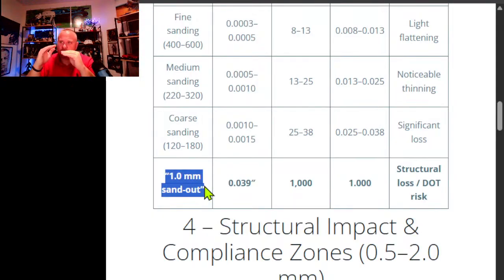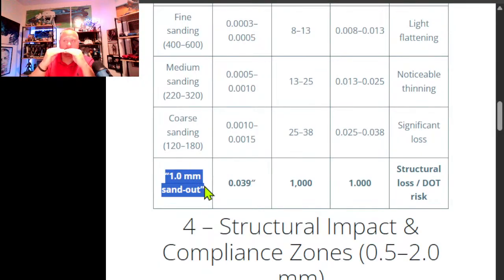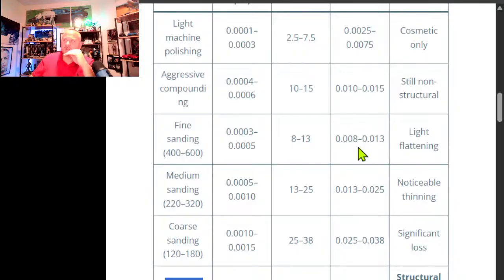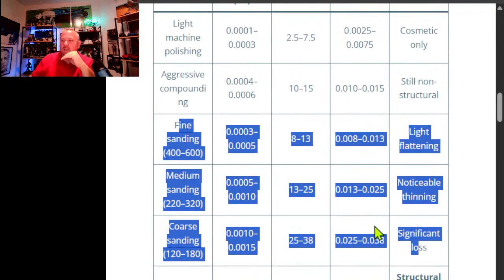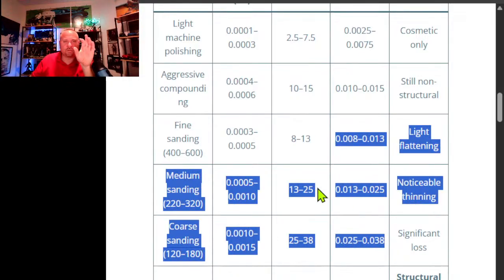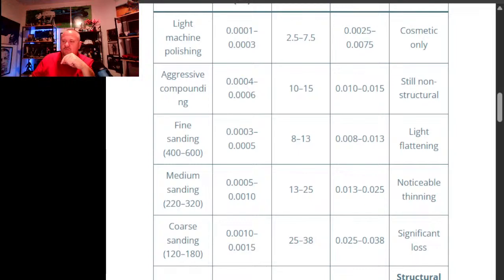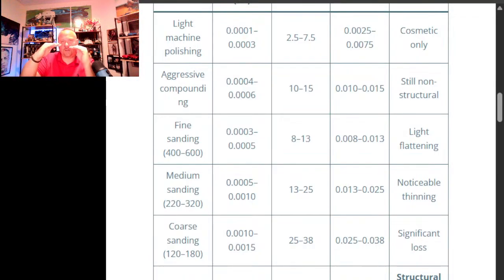So at a 320 grit, you remove the material, you now have the surface smooth, but now the person, what is being shown out there is they're going from 320, 400, 600, 800, and then getting to polishing, which takes off very minimum. But when you're talking about each progressive step of sanding, you're removing this amount of material all the way up. As you're stepping up, when you stop right here, from here to here, you add up all these numbers, and that's how much material in total that you removed. On top of this is the 1 millimeter that you've already removed, just to get to a part of the surface where it removed that gouge and where you leveled that surface out.